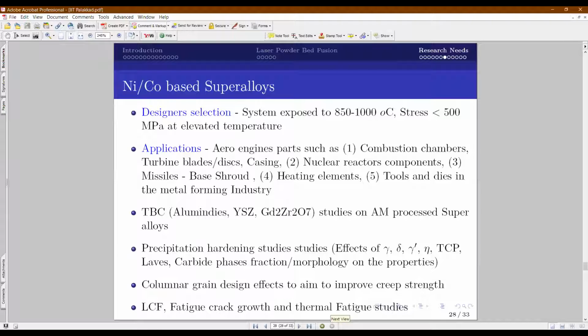Going to the next level, that is nickel or cobalt based superalloys. When the temperature is in the order of 1000 and stress at the temperature is less than 500, typically superalloys are used, like in combustion chambers, turbines, casings, nuclear reactor components, missiles, heating elements, and in tool and die industries, like tools and dies in the metal forming industries, which are usually superalloys. And to improve their temperature performance, superalloys are generally coated with thermal barrier coating. In addition to that, they make it a single crystal, and cooling channels are also introduced. Whether the conventionally used TBC is applicable to 3D printed superalloys is a subject of debate till now. So we can work on those areas and develop a TBC for the superalloys.